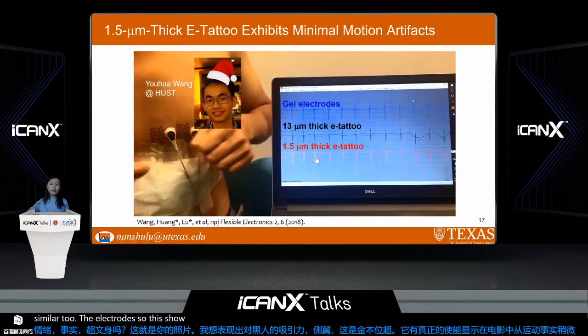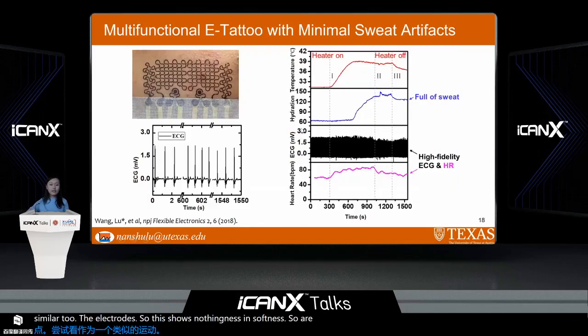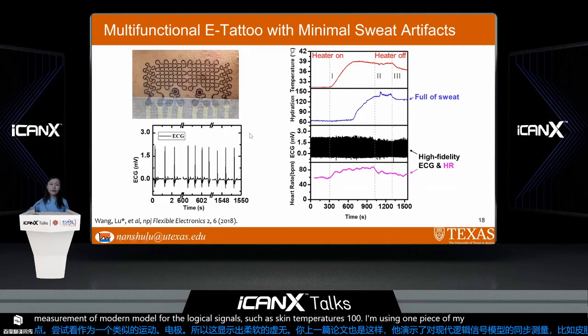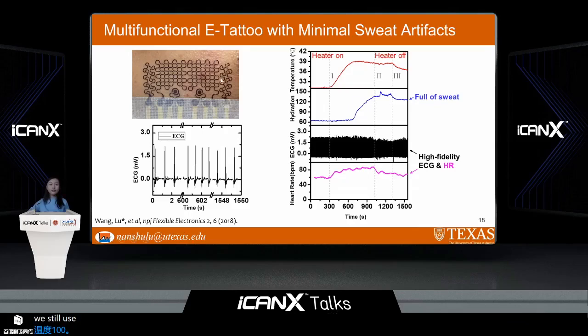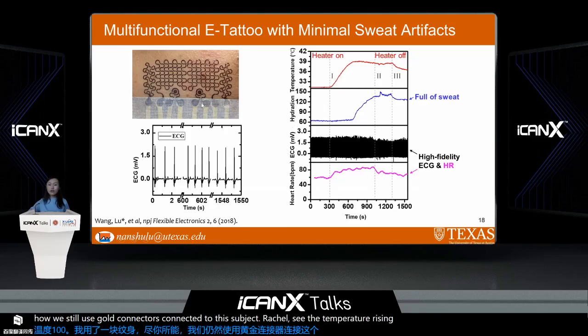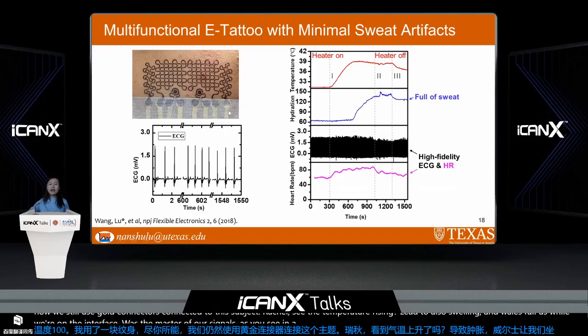Also in Youhua's paper, he was able to demonstrate the synchronous measurement of multimodal physiological signals such as skin temperature, skin hydration, and ECG, using one piece of multimodal e-tattoo. As you can see, at that time, we still used gold connectors to connect to this e-tattoo. And we were heating up the subject. We can see the temperature rising also led to sweating. And when it's full of sweat, however, on the interface, we still measure very reliable ECG signals, as you can see in a blown-up view here. The sweating is not affecting the performance of the e-tattoo.